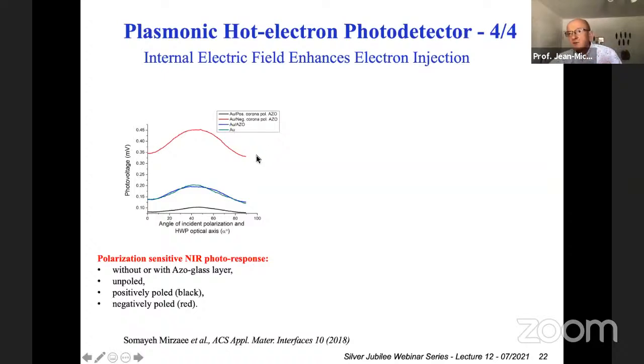Okay. When I say the density of charges multiplied by the area, the photovoltage is directly the quantity of charges that were generated by the hot electron emission divided by the capacity of the material. So in that situation, if we don't change too much the capacity, we have the same photovoltage that was detected by putting a layer of azo glass on top. But if we polarize the azo glass in two directions, we can polarize it positively or negatively and orient the dipoles.